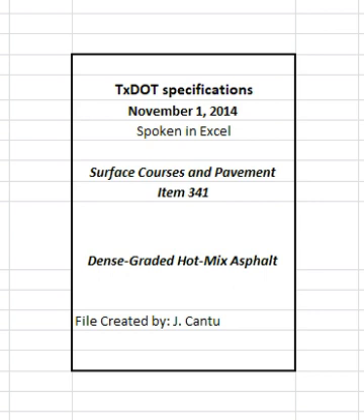4.7.3.4 Screed heaters. Turn off screed heaters to prevent overheating of the mat if the paver stops for more than 5 minutes. The engineer may evaluate the suspect area in accordance with Section 341.4.9.3.3.4, Recovered Asphalt Dynamic Shear Rheometer, DSR, if the screed heater remains on for more than 5 minutes while the paver is stopped. 4.8 Compaction.